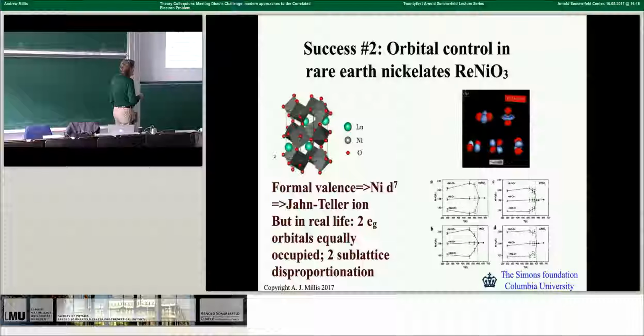There are 4 of these different materials. These are the nickel oxygen, the mean nickel oxygen bond from this octahedron or that octahedron. You see that above this temperature, which is probably hard to read but is sort of twice room temperature, the octahedra are the same. You go below this temperature and you have a short bond one and a long bond one, and this is quite generic.